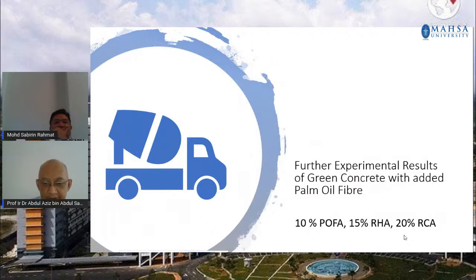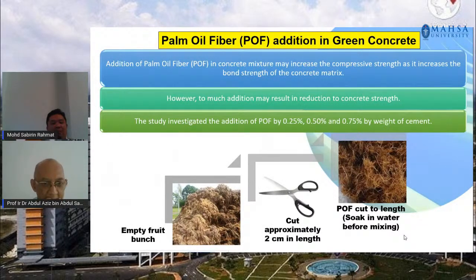Okay, now I want to further discuss the results of the green concrete when we add palm oil fiber, or POF. All right. In this study, the palm oil fiber we obtained from the factory, from the palm oil industry, and we cut the length of the fiber up to 2 centimeters in length. They are also soaked in water to avoid them being too dry. The study also investigated adding palm oil fiber at 0.25%, 0.5%, and 0.75% by weight of cement. This is the percentage that we use based on past literature review. This is the common percentage used by most researchers in adding palm oil fiber in the cement.